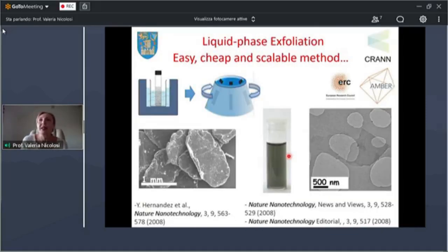So the journey with 2D materials started really at the end of my PhD back in 2008, where the group I was working with, Jonathan Coleman in Trinity College Dublin, we developed together a methodology to take thick graphite flakes that we bought very, very cheap, a bucket of 2.5 kilos for about 30 euro. And we managed to develop a very easy and cheap and scalable method to select suitable organic solvents, very common solvents that are capable of interacting with the matter in a way that when you provide a little bit of energy or shaking, in this case, we provided that by ultrasonication, you could allow the solvent to get entrapped between the layers and then eventually take the layers apart.